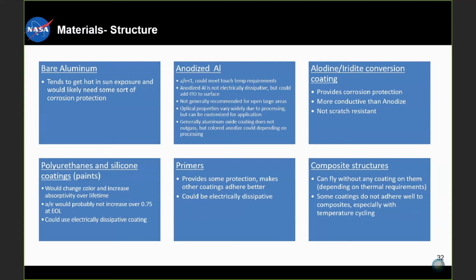Anodized aluminum is not electrically dissipative, but you could add ITO to the surface to meet that requirement. It also is not generally recommended for open, large areas. Its optical properties vary widely due to processing, but it can be customized for each application. And then generally, aluminum oxide coating does not outgas, but a colored anodize could, depending on the processing. The next is iridite conversion coating. This provides corrosion protection. It is more conductive than anodized, although it is not going to be scratch resistant.